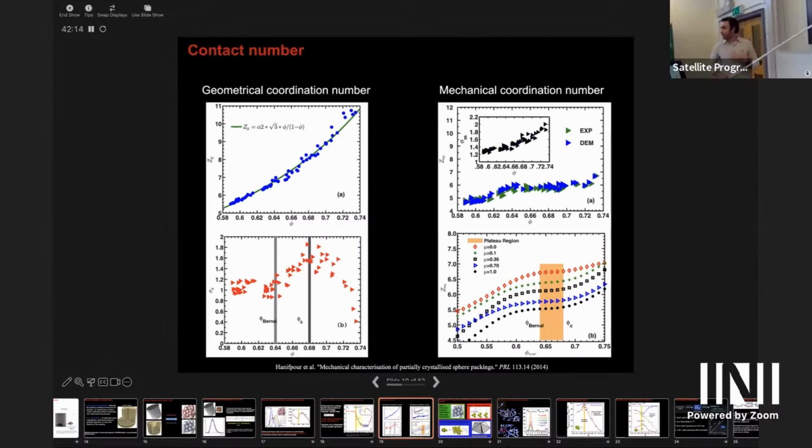However, if you look at the fluctuation of the contacts, so how many contacts per grain you have and how this evolves as the packing density increases, you get a much richer picture. While the fluctuation remains more or less constant in the disordered phase, you start getting an increase up to 80% in contact fluctuation, meaning a lot of grains form and remove contacts continuously along the way. And that is deeply connected to this specific heat before everything drops down to much below the disordered region.